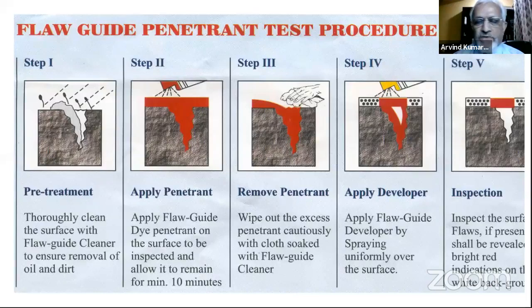The first one is that we need to clean the surface. Cleaning has to be very, very proper to ensure that all the dust, oil and foreign material is removed, and the cavity which we are expecting to be a defect should be very clean. And after cleaning is done thoroughly, then you have to apply the dye, which we call the penetrant. There are various methods of how to apply it, which we'll be seeing in other slides. Once the dye is applied, you have to hold for some time, which we call the penetrant dwell time. Dwell time is the time where we allow that dye to enter the cavity or the crack or whatever defect we expect.